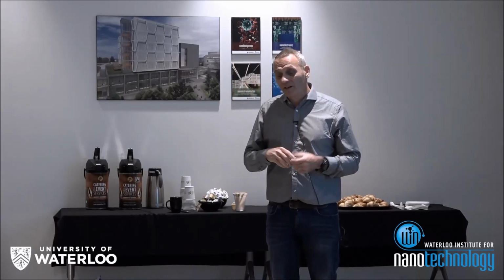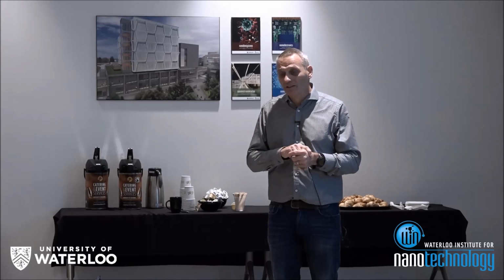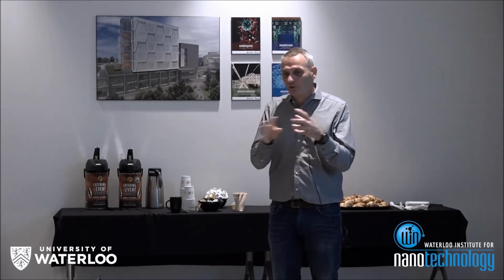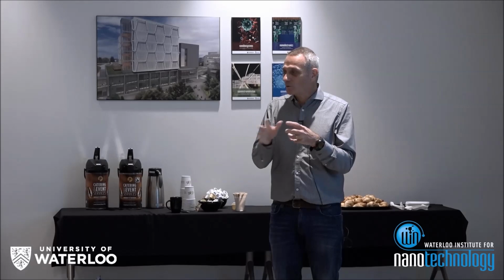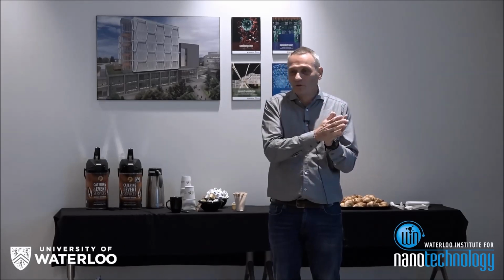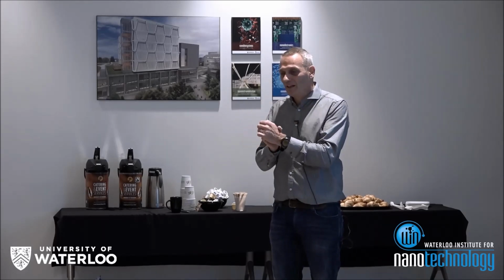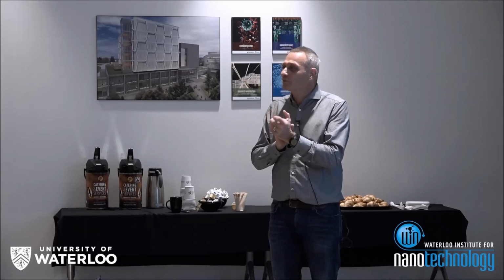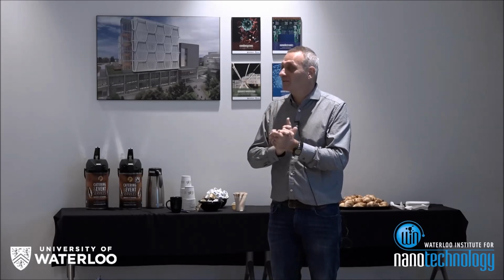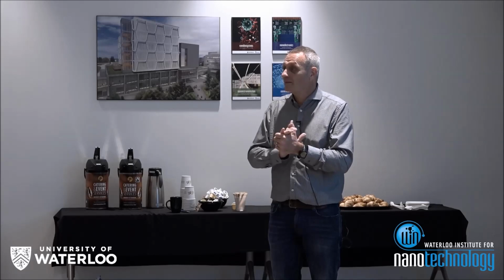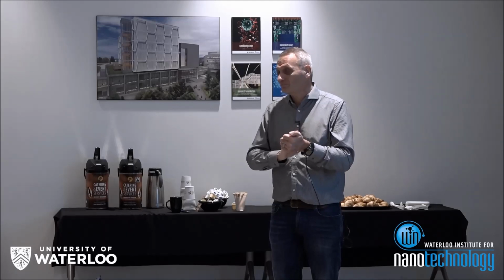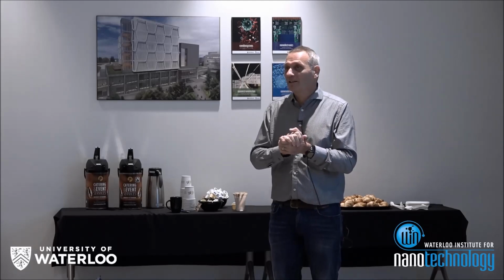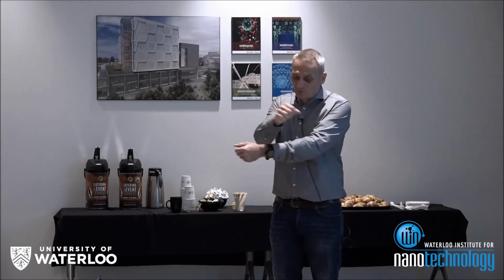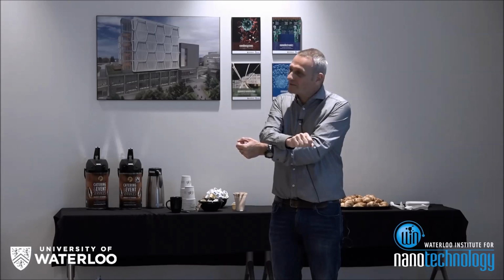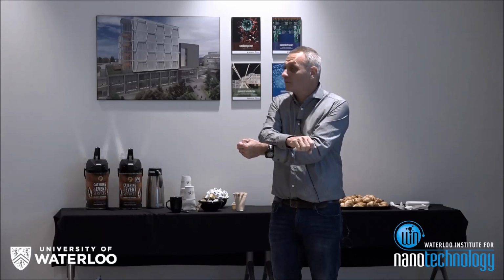The other point is that we chose from the beginning to do air annealing, knowing that it was very different compared to vacuum. So we don't want to repeat all we have done in air again in vacuum. And I think it was maybe less reproducible as well. Mainly, the PVP is less degraded, and I think decreasing the junction resistance was a bit less powerful as well.